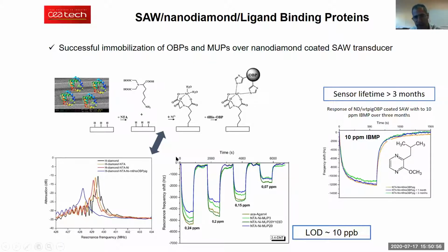This is the typical response that we're getting. Here we're looking at the response for 4 different sensors. 3 of them are functionalized with MUPs, 1 with OBP, and you can see that they're very sensitive. Here we are measuring 70 ppb of 2,4-DNT, which is an analog structure to the explosive TNT. So we are very sensitive, and you can see also that the sensitivity varies from sensor to sensor because the affinity of the different proteins towards DNT is different.